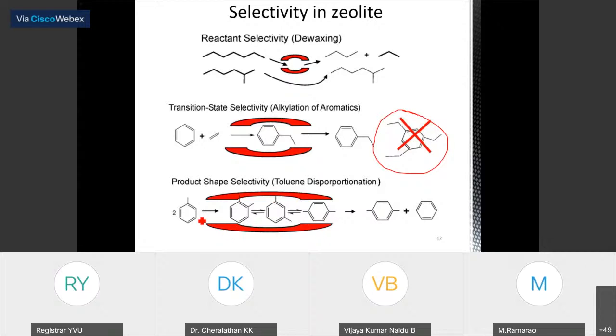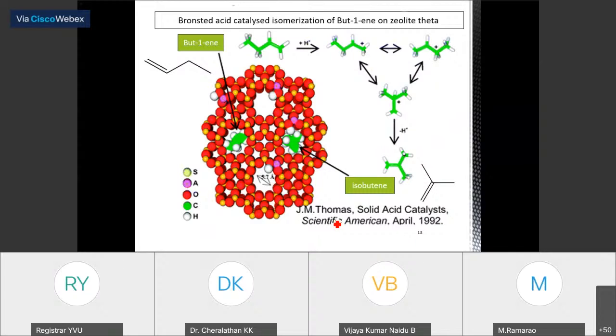Also, this kind of product selectivity is possible. For example, if you alkylate toluene, this alkylation may take place in the ortho position, meta position, and para position. Generally, it will take place like that. But when you perform the same reaction in the micropores of the zeolite, due to the restrictions induced by the pore, you will selectively get this para alkylated product. So this kind of product selectivity is possible. That is why zeolites are attractive materials as catalysts.